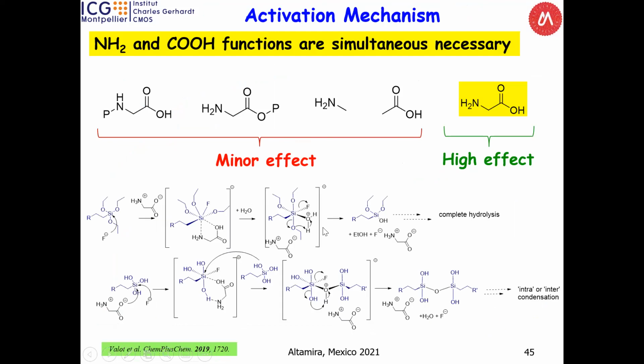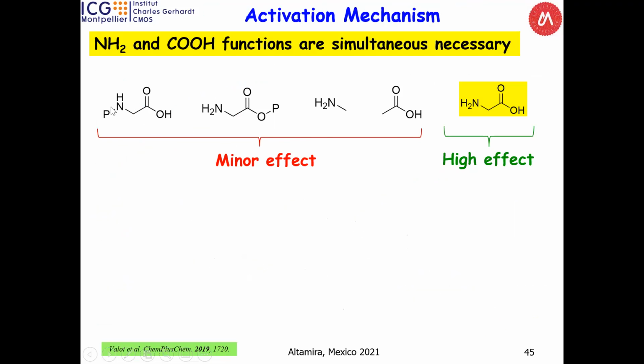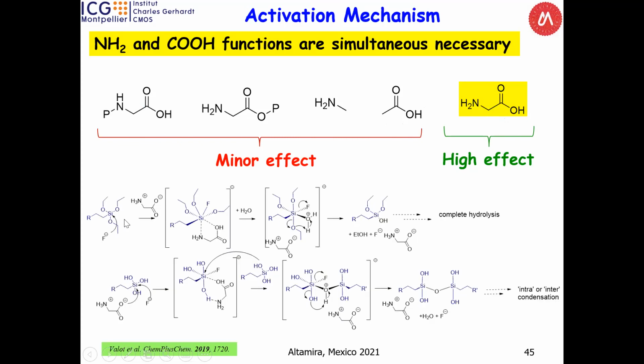I would like to explain the effect. There is a minor effect if you protect your glycine, amino side or acid side. If you take a mixture of methylamine or acetic acid, there are no effects. However, when you add this one, a huge effect. How do we explain that? After coordination of F-, the amino acid becomes a chelating group to increase the reactivity of the silicon center. And then water can attack, and the hydrolysis and polymerization take place. It's not necessary to explain more, but all this was controlled by silicon NMR.